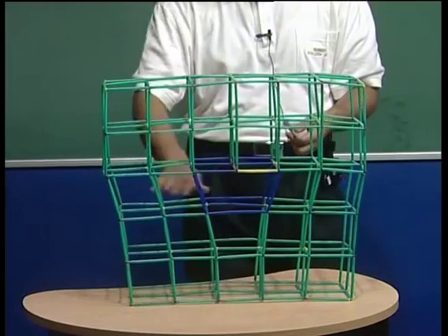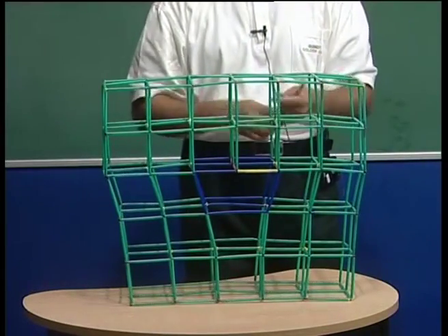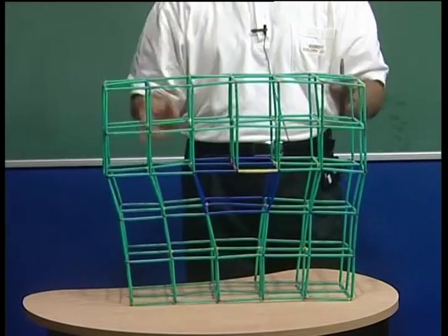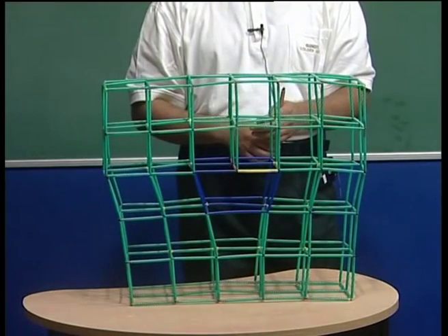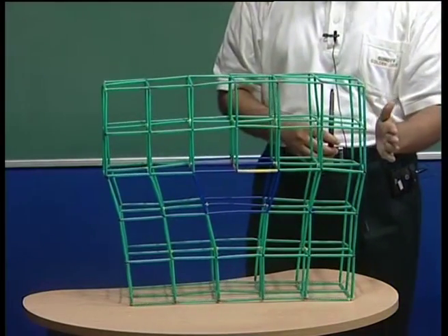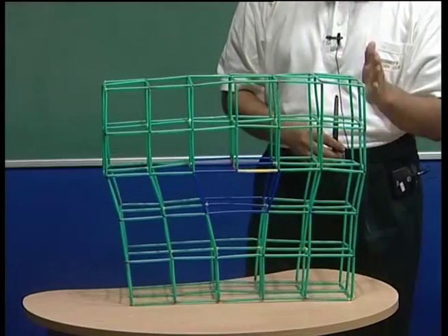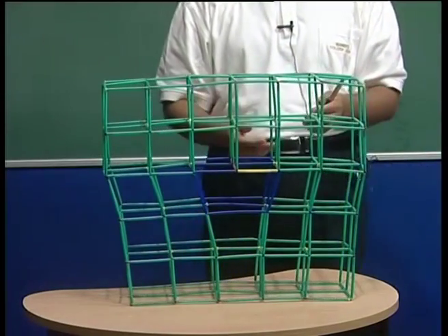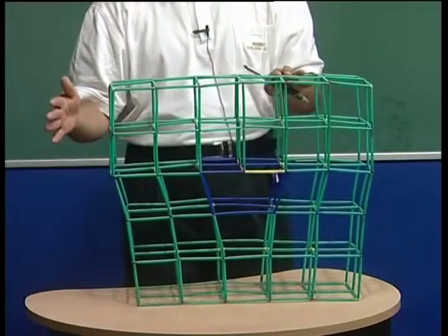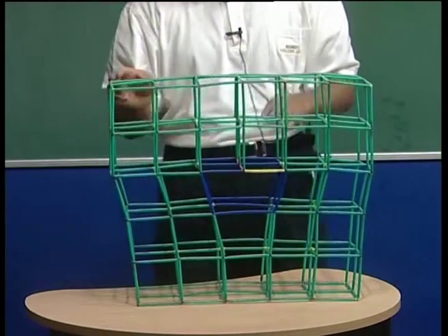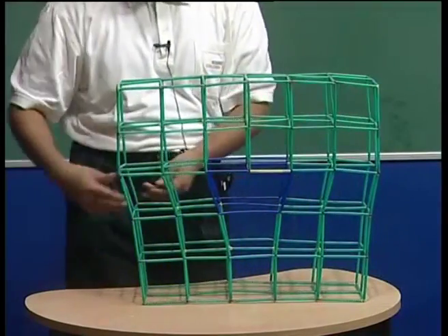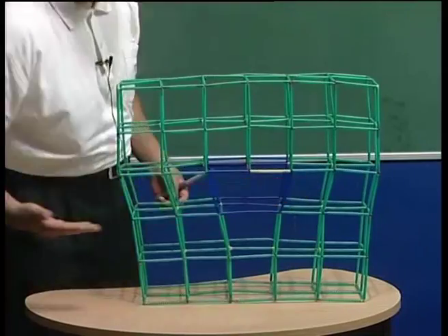So the plane common to both the T vector and the B vector for an edge dislocation is my slip plane. Now why do I call it the slip plane? That takes us back to the experiment or the model in which we had pushed an atomic plane, pushed the side of a crystal, so that we pushed in a half atomic plane. This same thing can be visualized here. Suppose I push this part of the crystal, and therefore I create a step on the surface, and this plane moves in here. So this plane, which is now the middle plane, the plane residing here, would be my slip plane.